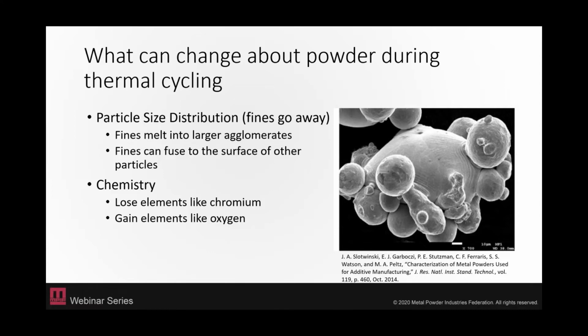So these are the things that are going to change while you're thermally cycling. Your fines are going to go away, and those fines are part of that nice bell curve that you want with your particle size distribution. They can either melt into larger agglomerates or just stick to a nearby larger particle, like is happening in this image. And then the second way your powder quality is affected is by the chemistry changes from thermal cycling.